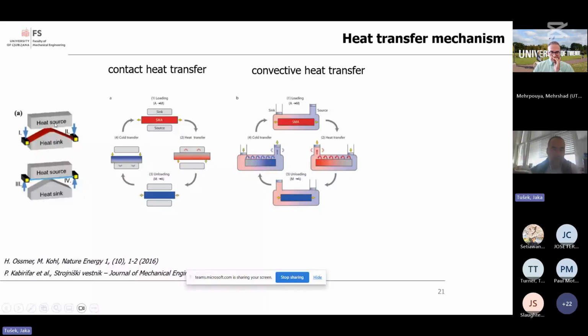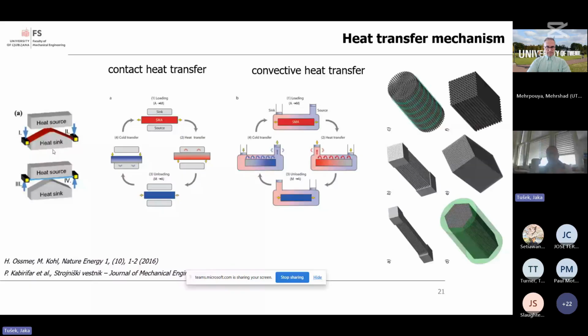This concept is interesting for miniaturization, for example. It can be useful for microcooling because it's somehow limited to rather low absolute cooling or heating powers, and these systems are being developed in Manfred Kohl's group at the Karlsruhe Institute of Technology. On the other hand, convective heat transfer applies macroscopically porous materials like regenerators, through which a heat transfer medium can be pumped in the counterflow direction and can essentially provide larger absolute cooling or heating powers because they contain a larger amount of elastocaloric material.